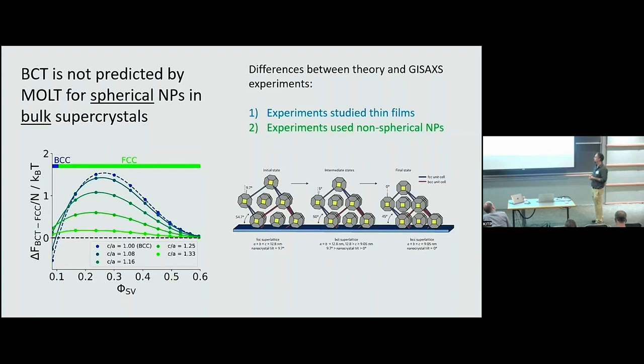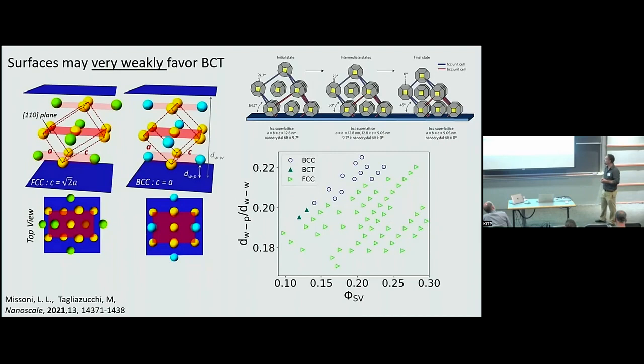All right, so the first one we looked at was the effect of the surface. So we took just three layers of nanoparticles and we sandwiched them between two surfaces. In this phase diagram, I'm showing you the density of the solvent and the distance between the nanoparticles and the surface. And you see a lot of BCC, a lot of FCC, but only 2 points were predicted to be BCT. So this means that even though the surface may stabilize BCT, I don't think it can really explain it, because you really get a lot of experiments showing BCT phases in nanoparticle superlattices. Almost none in large micrometer size spheres, in colloidal crystals of micrometer size particles, but in superlattices made of nanoparticles with alkanethiol ligands, they show up a lot.